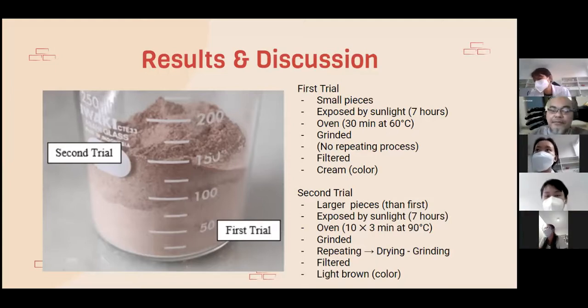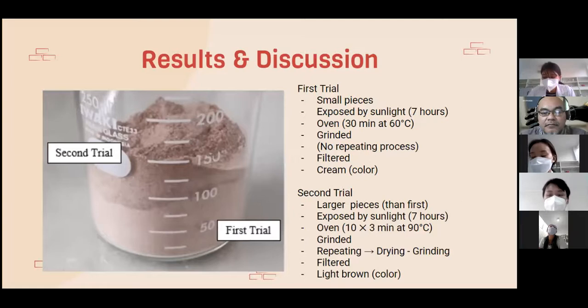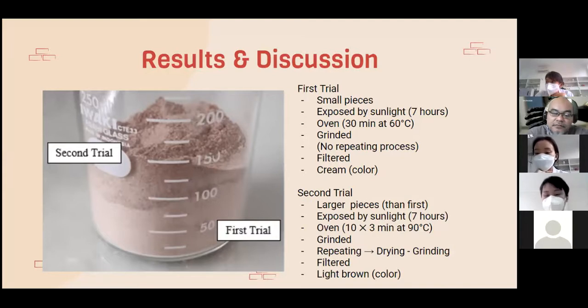And then we just exposed it to sunlight, for the same amount of time. And at the oven time, we had a problem. The first one is actually the right one. We put it in for 30 minutes at 60 degrees Celsius, while the second one, we intended to have a faster result using a higher oven temperature, hotter, and it is written that 10 times 3. It means that for the first, we intended to take it only for 10 minutes, and then after we checked it, it was still moist, and we put it again, and we checked it again after another 10 minutes, and it was still moist, and then we did it again 3 times.